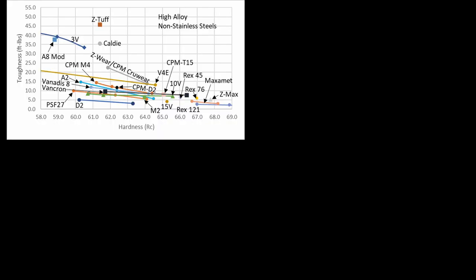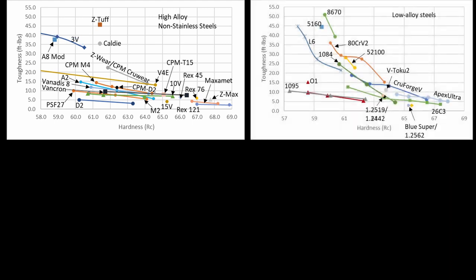Comparing the toughness of Z-Tuff with other steels, it's amazing. So 61.5 Rockwell, over 40 foot-pounds, that's better than any other steel I've tested. Even 8670 and 5160, which also get in that same range of toughness, do that at like 1 to 2 RC lower hardness.